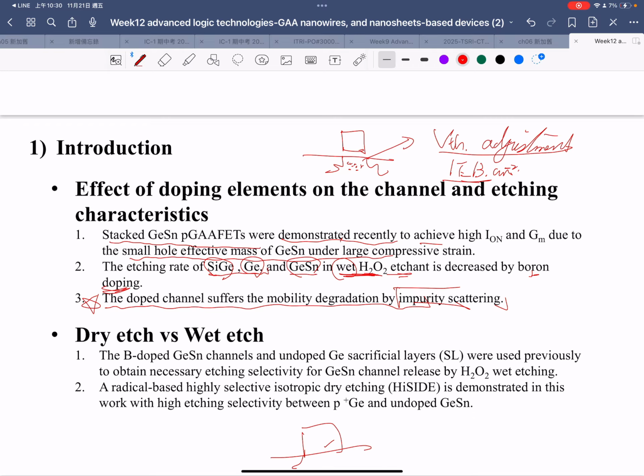Usually we have to use very high doping to suppress the short-channel effect. Unfortunately, a higher dosage will cause lower mobility. So after that, we use a pocket or halo or anti-punchthrough implant. This is anti-punchthrough; the purple is anti-punchthrough to suppress the short-channel effect. So we keep the channel in low dopant concentration. This is because a doped channel suffers mobility degradation due to impurity scattering.